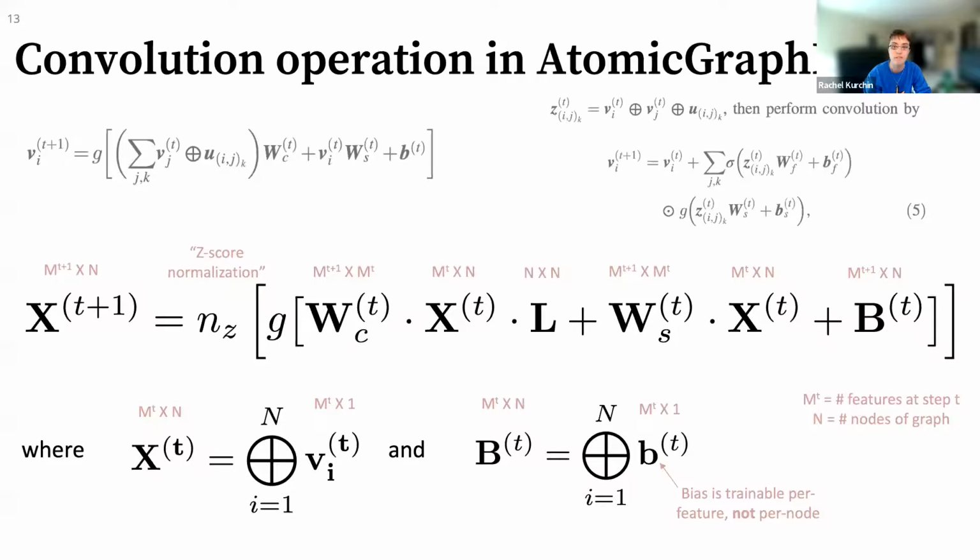There's also support for another option, which is based on the Voronoi tessellation of the crystal. So if you break up the crystal into these Voronoi cells, every atom is surrounded by the volume in which every point in that volume is closer to that atom than to any neighboring atom. And this will in general give you some sort of polyhedron. This has the advantage that it also gives you a consistent way to determine what the neighbor lists actually are.